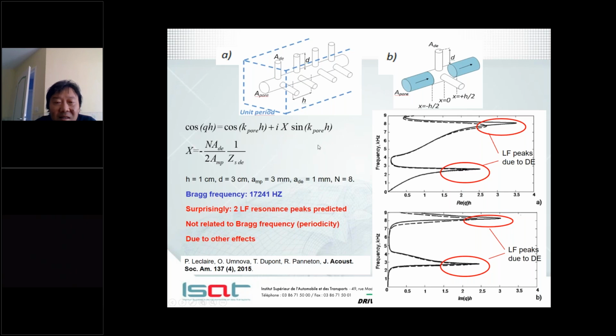The important parameters in this are: H is the periodicity, K is the wave number in the main pore, and Q is the wave number in the effective fluid that represents this structure or its rigid frame. But one important parameter is this X, which represents a non-dimensional admittance. And in this parameter, you have N, the number of dead ends per node, A, the cross section of one dead end, AMP, the cross section of the main pore, and the surface impedance at the entry of any dead end here. And this parameter is very important for future designs of materials.